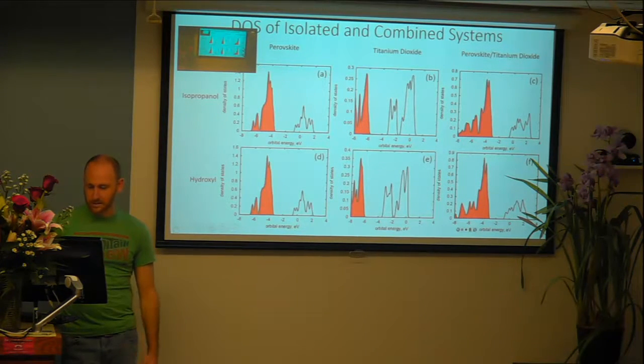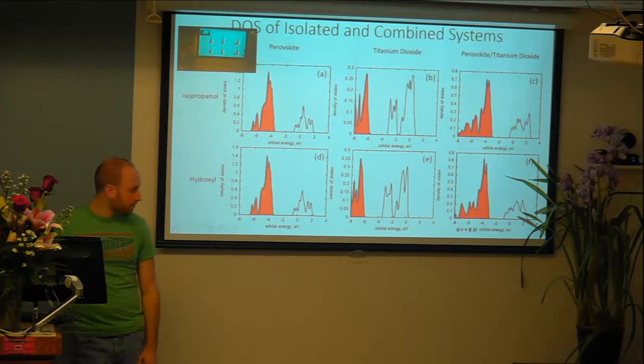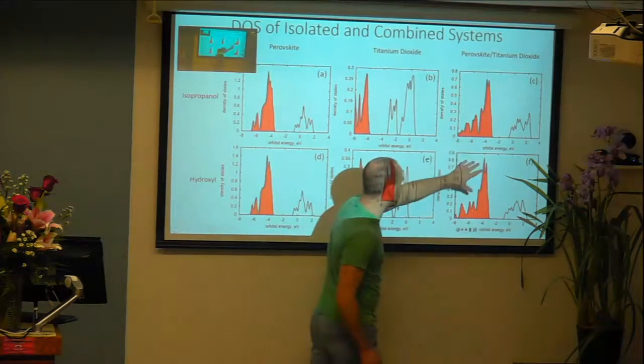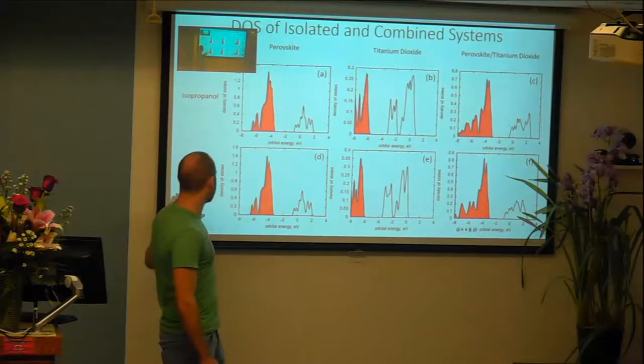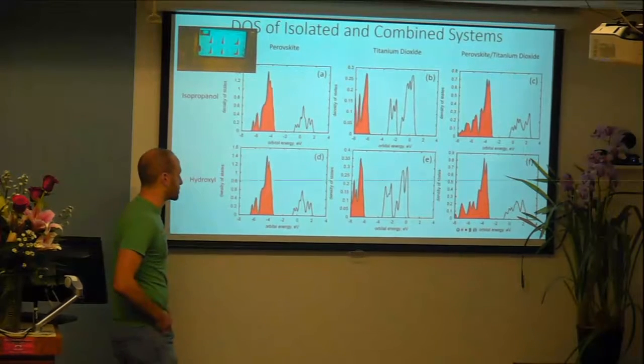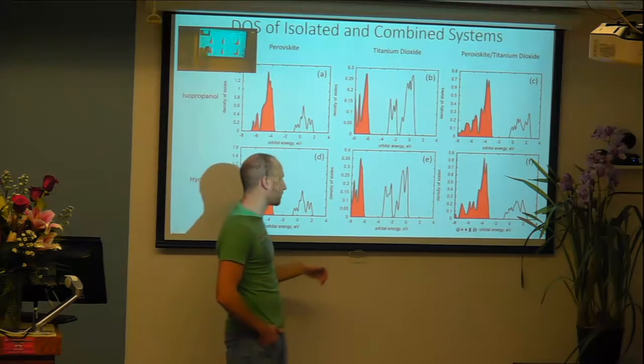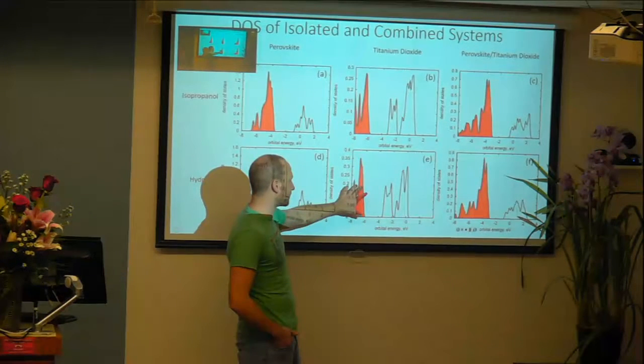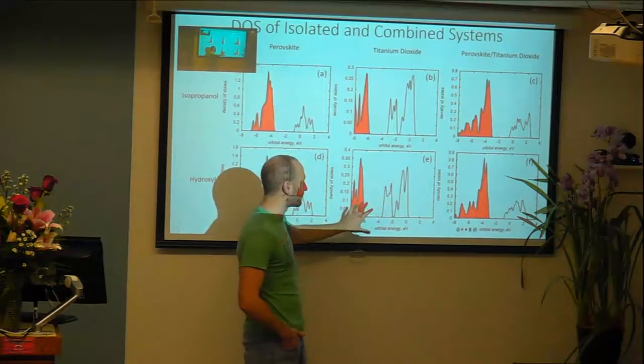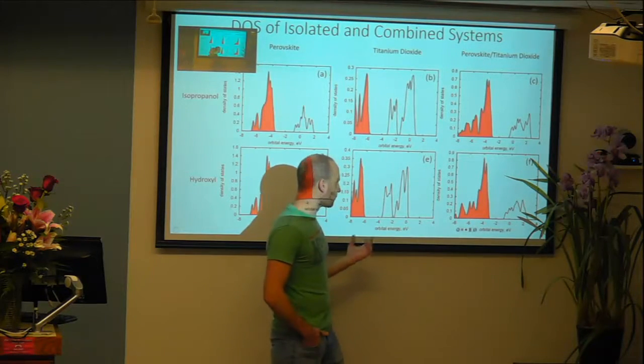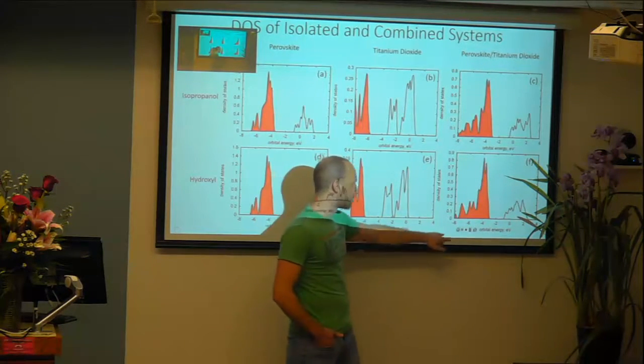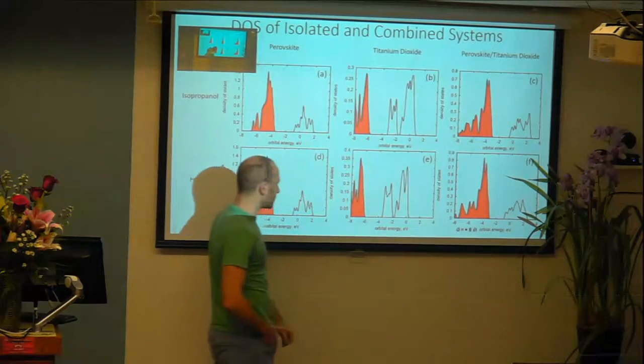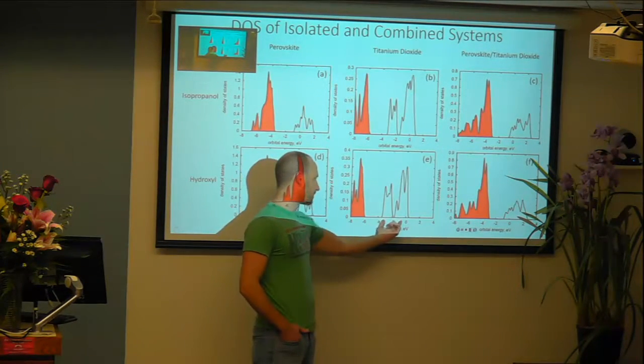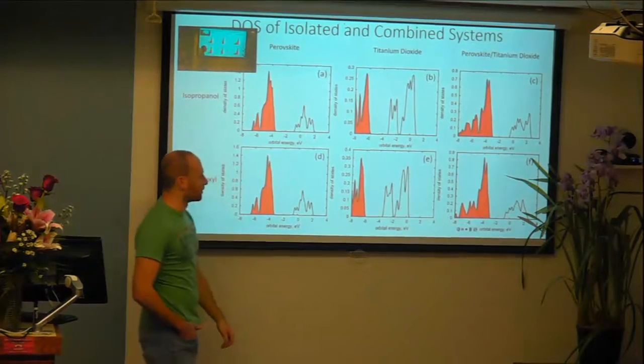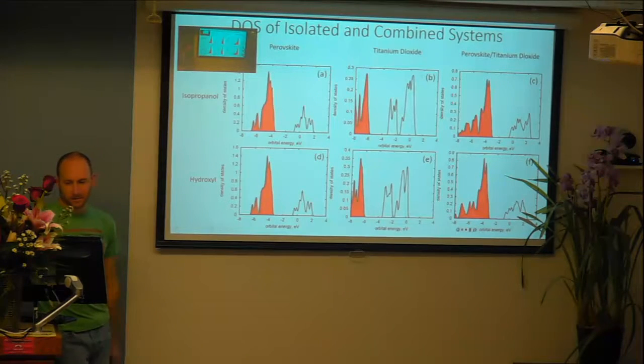These are some densities of states of the separated systems and then combined. These are all the isopropanol model, and these are all the hydroxyl model. The perovskite in both cases is essentially identical. There are some slight differences between the titanium dioxide, but largely they have the same structure. When you combine these systems, you get a different shape of the density of states. You end up losing a lot of the states from the titanium dioxide. It suggests that there is a significant interaction between the two when you put them close together.